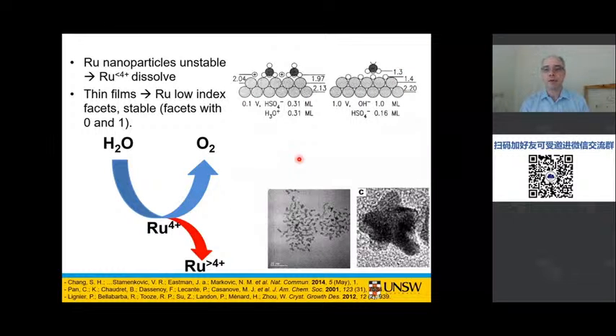So we kind of drew our inspiration from quite a bit of the old thin film research on electrode catalysts. So there was some nice work done just on thin film electrodes with ruthenium about 20 years ago that really showed that if you could have nanoparticles of ruthenium which had low index facets for the electrode material, then for thin films, low index facet ruthenium was actually more stable. So when we say low index facets, we're really talking about facets that have Miller indices of 0s and 1s. So these are our low index facets. So these are the facets that we're chasing.